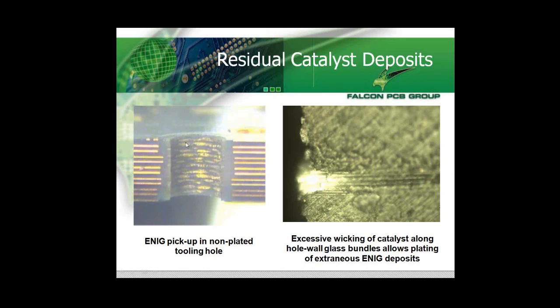We find this problem has been worsened by the use of lead-free laminates, whose curing agent is now Novolac, a phenol compound, rather than the old dicy-cured types that we've been using for many years before. The old dicy-cured laminates tended to be much more soft and malleable, but wouldn't stand the heat, of course, as well as today's Novolac cured. And although the heat resistance is there, it has a tendency to make the resin system much harder and a little more brittle, and does tend to cause little fracturing of the glass bundles and worsens this problem.